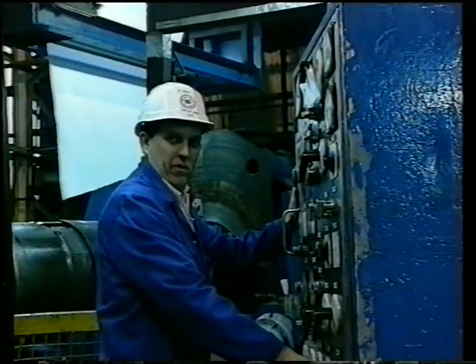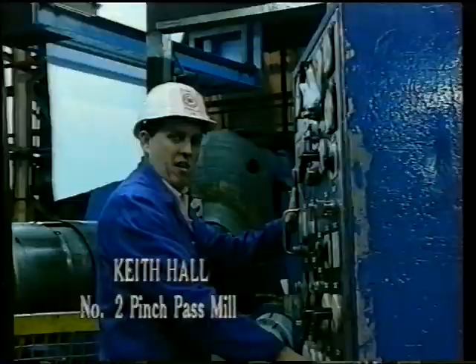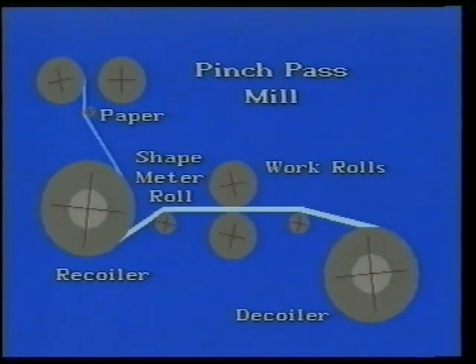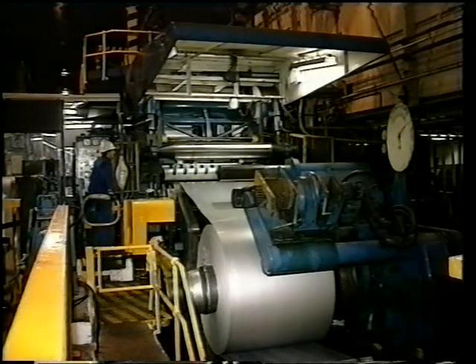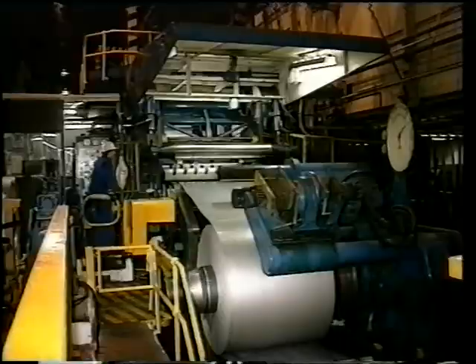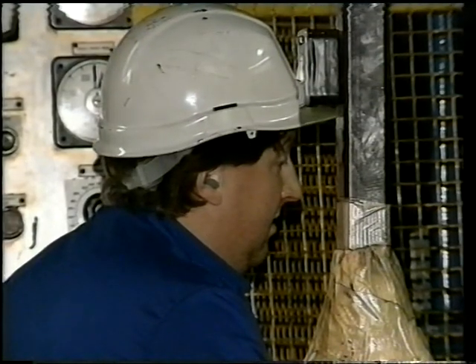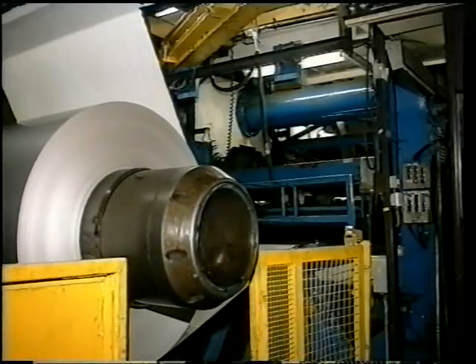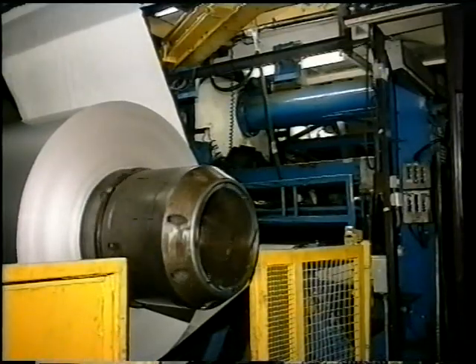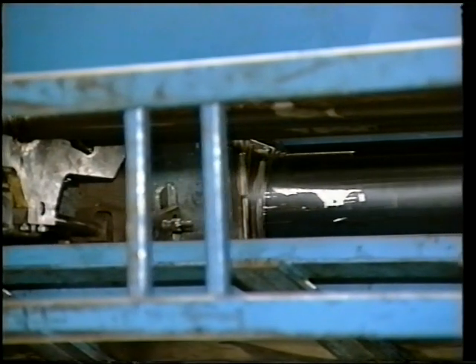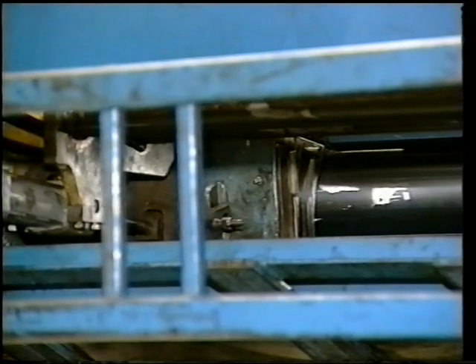The final process is a pinch pass on the pinch pass mill. This mill, installed in 1975, is a 2-high reversing mill and can roll up to speeds of 300 meters a minute. Using a maximum load of 1,000 tons, this mill improves the shiny finish for which stainless steel has become famous. Both mill rolls are ground to a high finish and are continuously cleaned by a wiping and polishing device whilst the rolling is in progress.